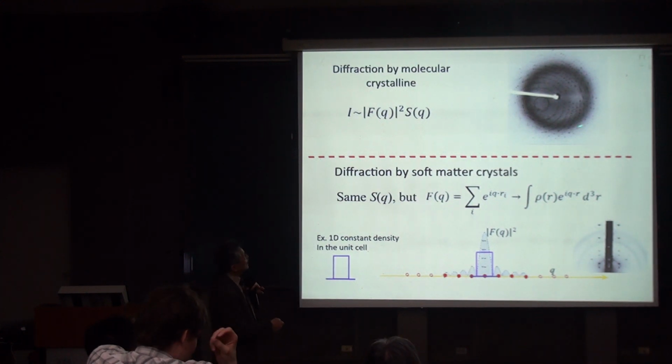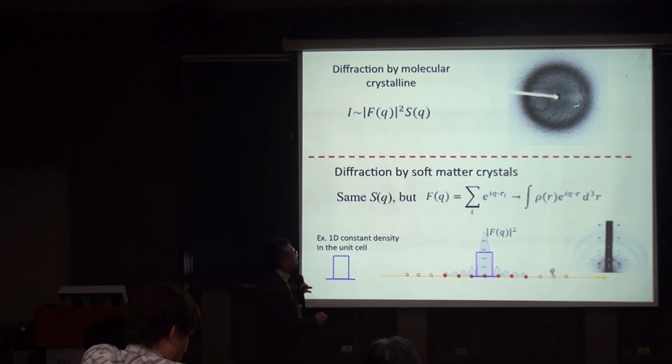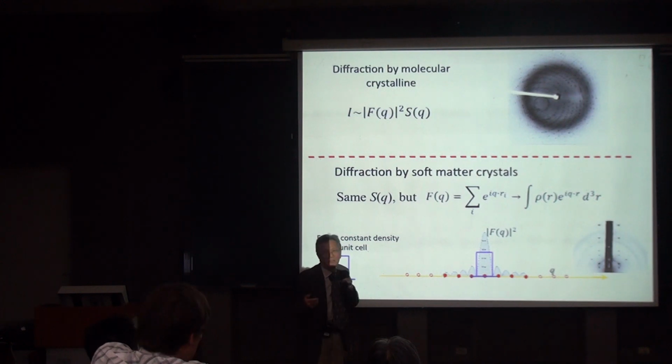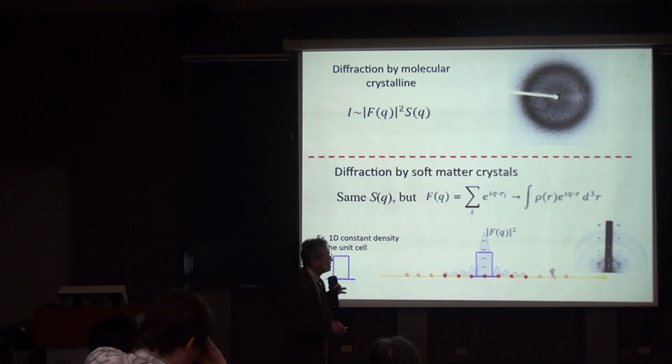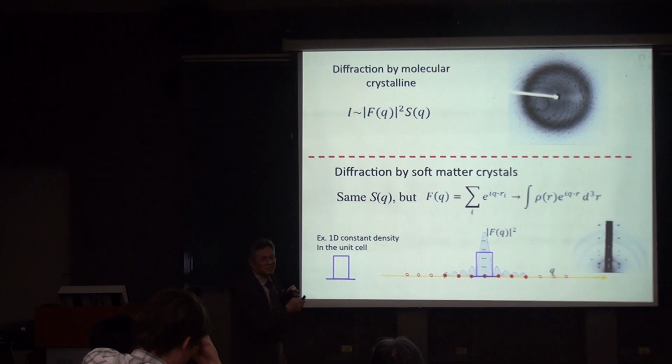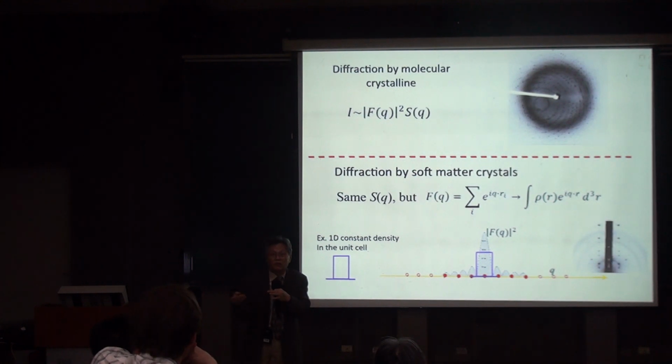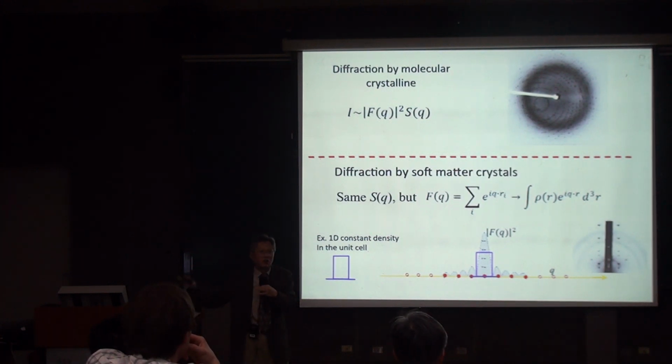You would think that, hey, if people can solve the phase problem, this must be a very simple problem, right? Firstly, a small number of peaks. Secondly, because of the symmetry, the amplitude may be a real function. Therefore, there's only either plus or minus. In other words, the angle is either 0 or pi. Only two choices.